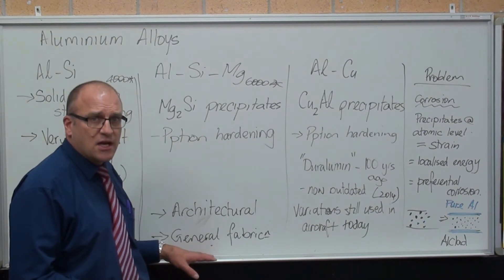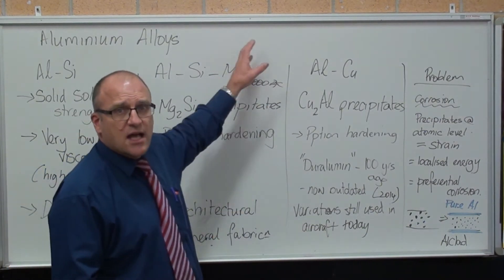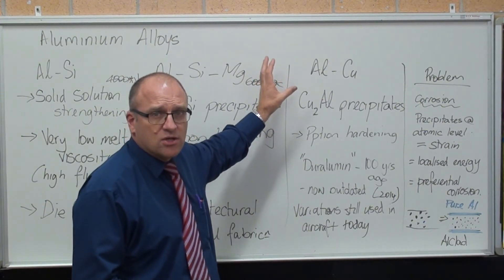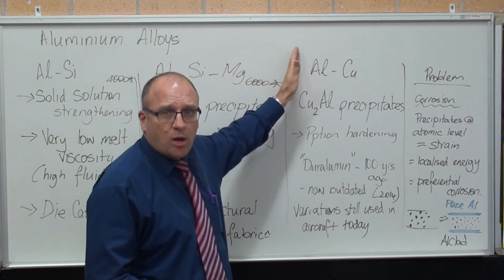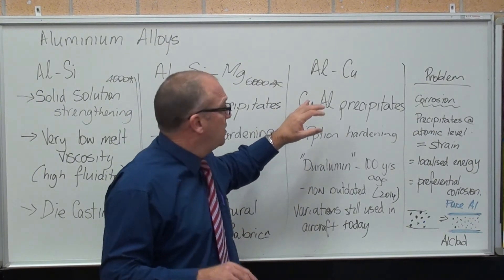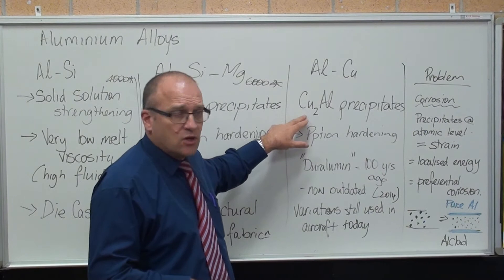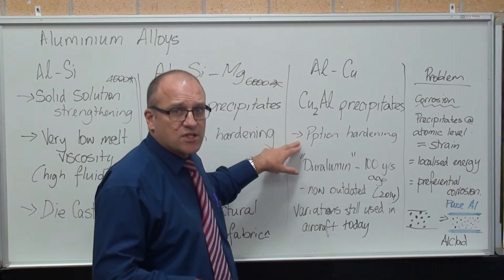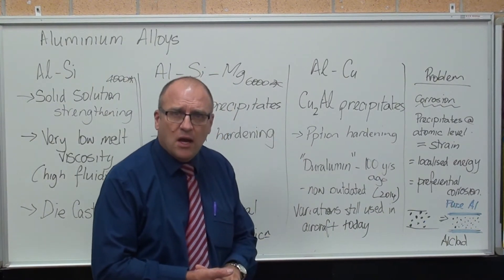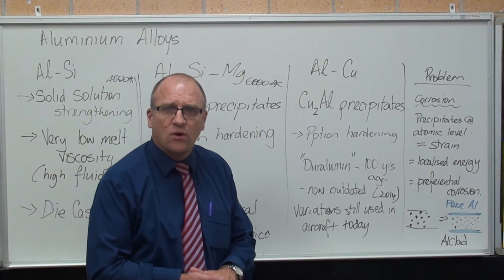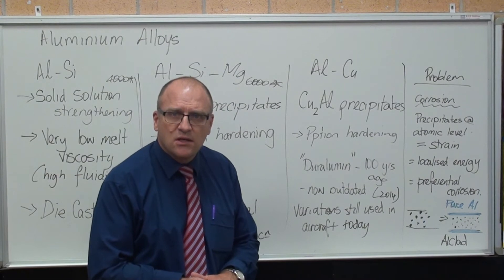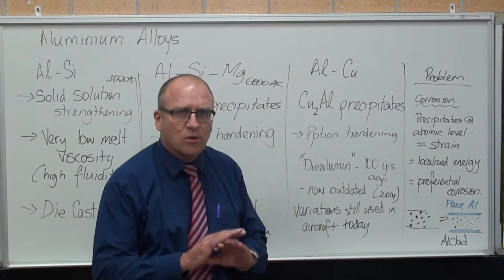The 6000 series is not used much in aircraft. The aircraft grade is aluminium copper, because of its better strength development and other metallurgical characteristics. The aluminium copper alloy is the 2000 series. It forms copper-aluminium precipitates which precipitation harden the metal. Textbooks often refer to Duralumin, patented in 1904, which ceased commercial development in the mid-1920s — a hundred years ago. It's an obsolete name.